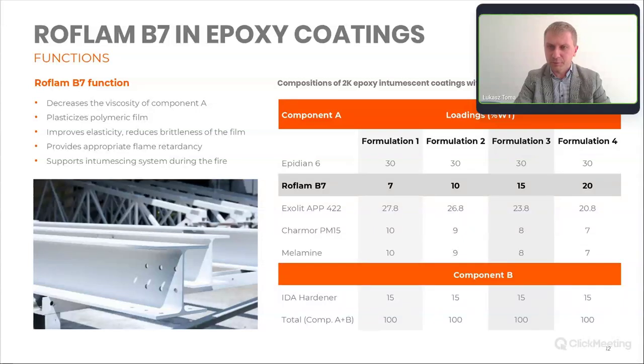So we made several formulations with different concentrations, starting from 7% in the total formulation up to 20%. As an epoxy resin in those formulations, we used a common product from our local market, from our local supplier, that is, in our opinion, good for this kind of application. This is a BPA-based epoxy resin. We also used an appropriate polyamine hardener that is recommended by the manufacturer to create a good coating. And finally, we have this intumescent system, APP, pentaerythritol, and melamine with the appropriate concentration that provide the intumescent effect of the coating. So on the next slide, you will see the results of the application evaluation.